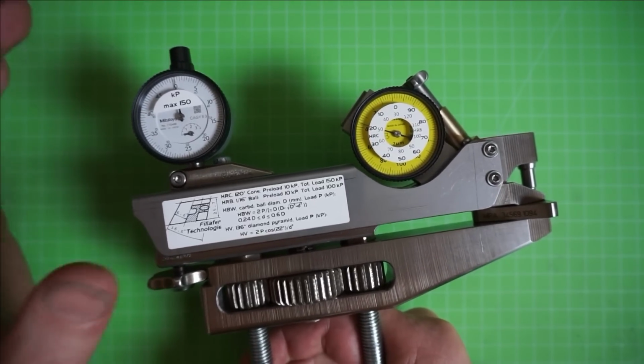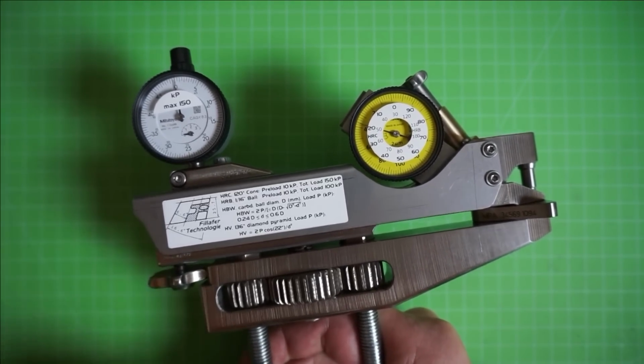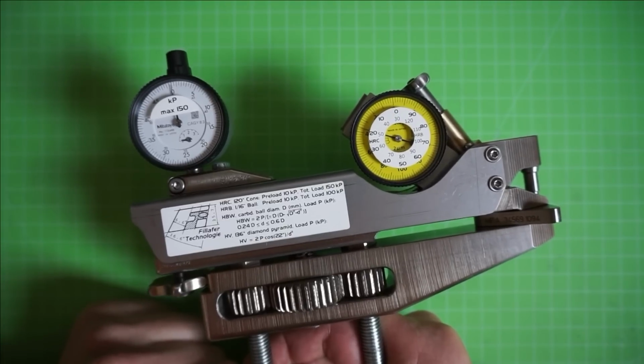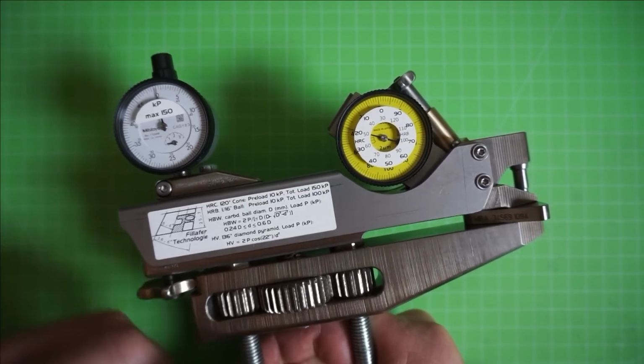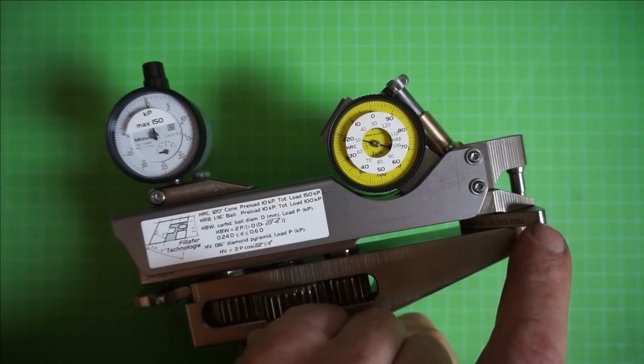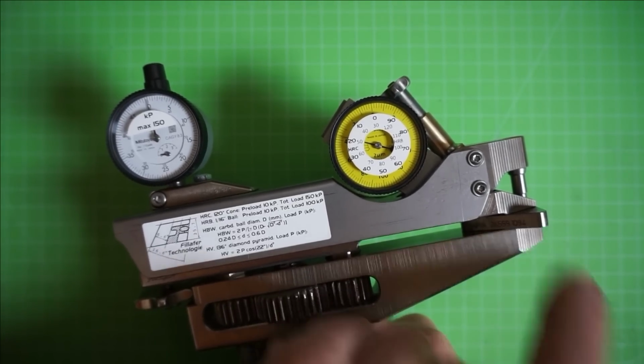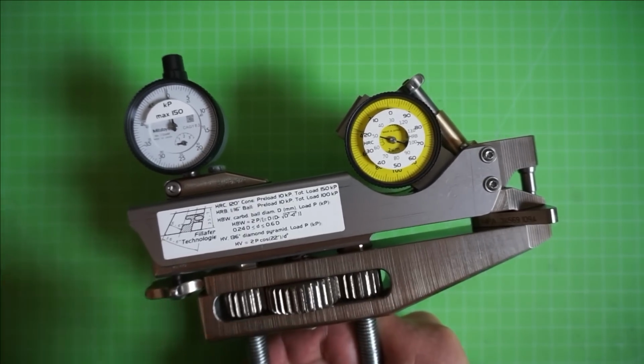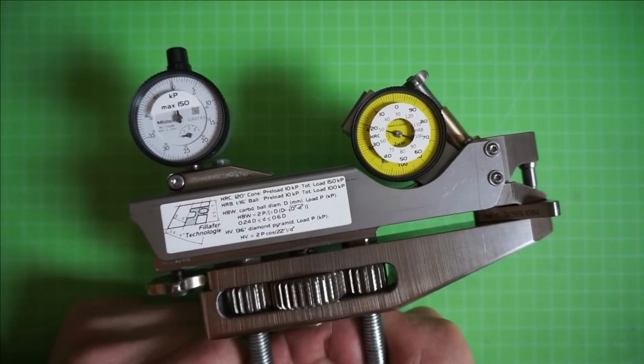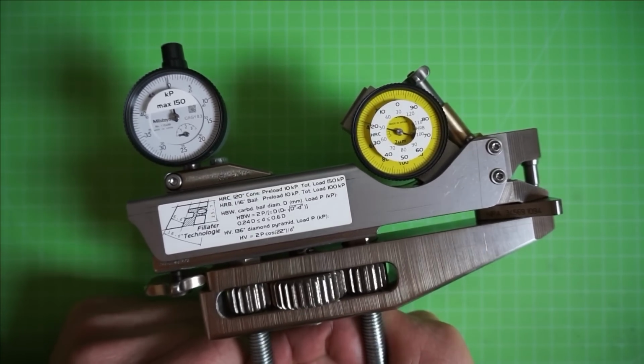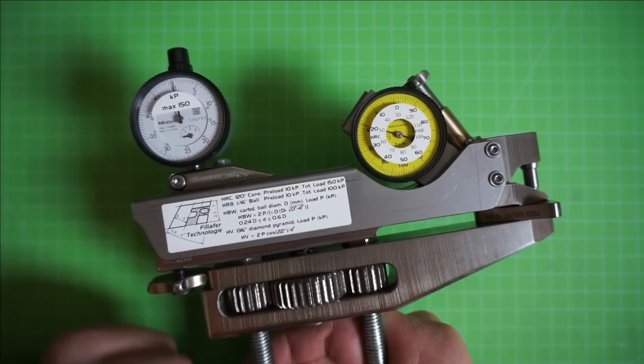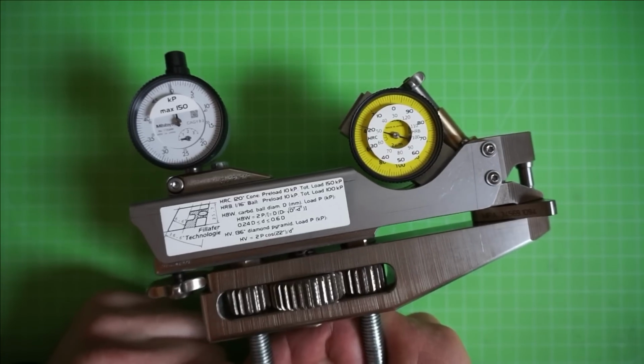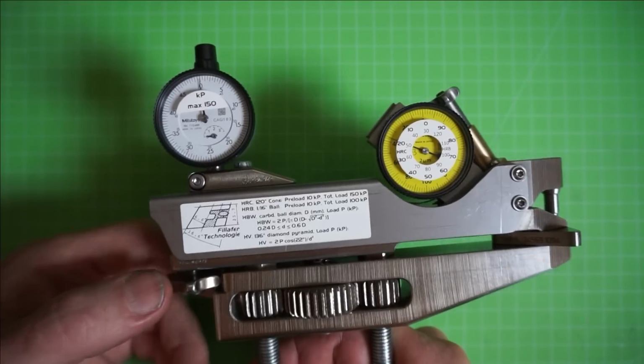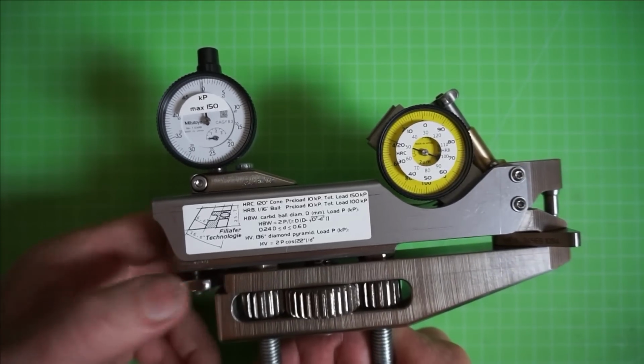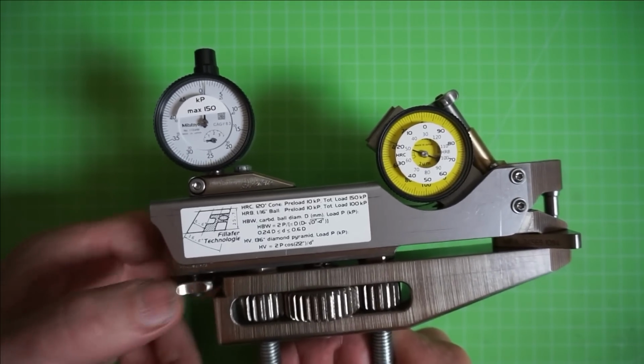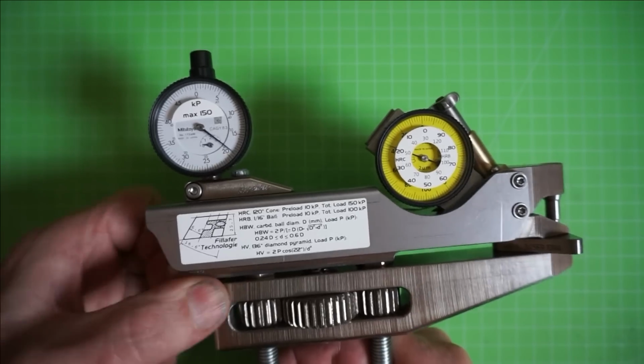In Rockwell they are already specified, but in Vickers and Brinell, always use the largest loads that you can. Of course then the indents get larger and you have to know what you can get away with without having to scrap the workpiece. But it's beneficial to have large indents, because then the errors and the result scatter get way smaller than with small indents. So okay, we said we want to use 50 kiloponds. Let's put that on.